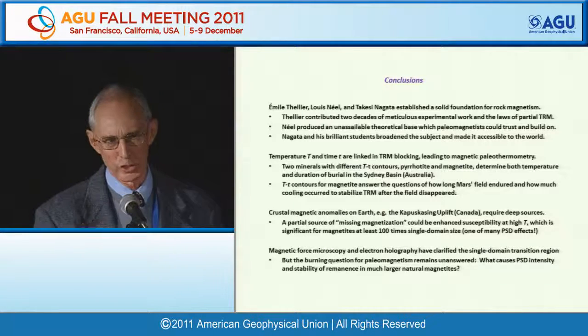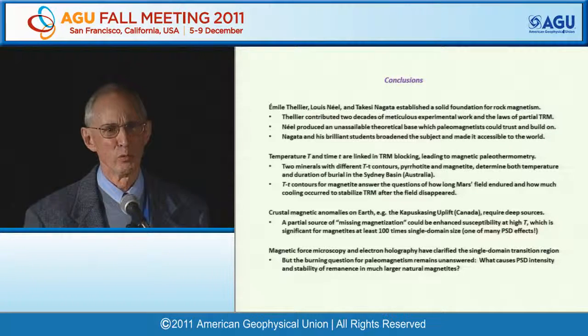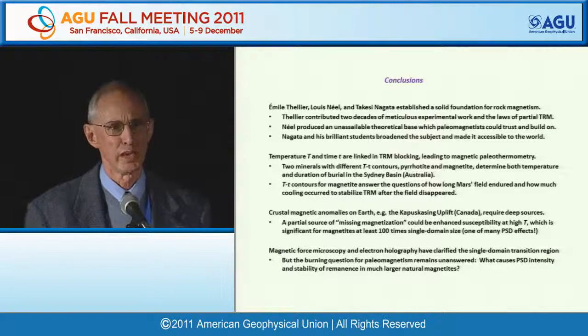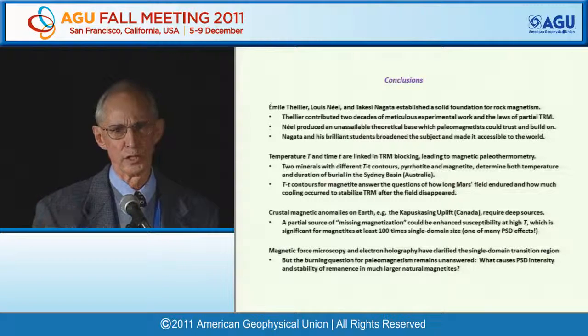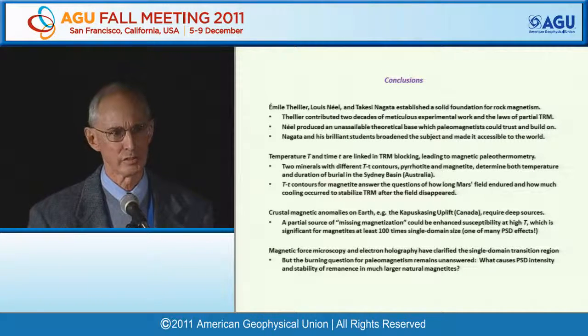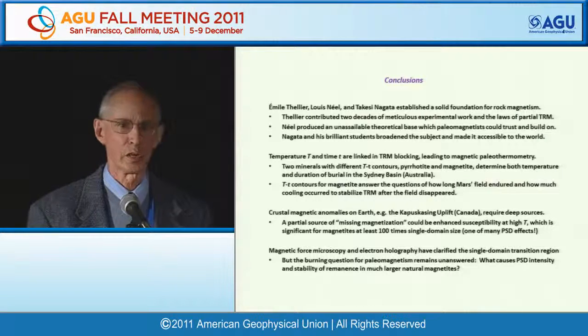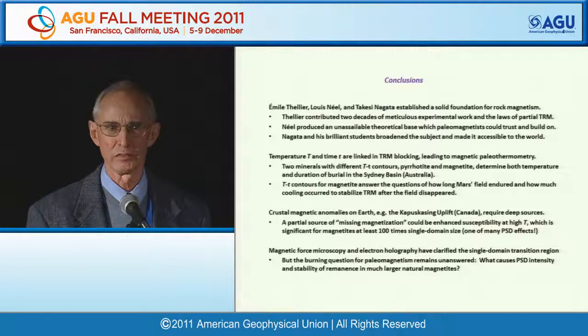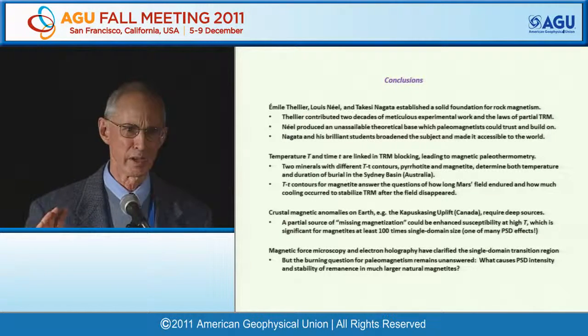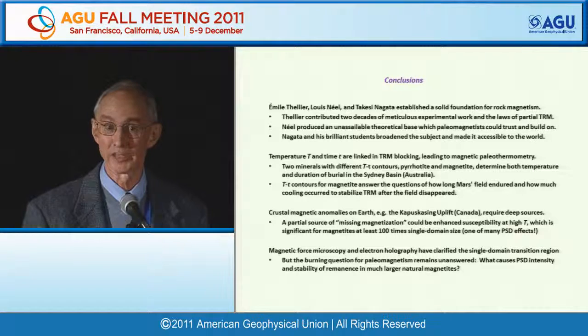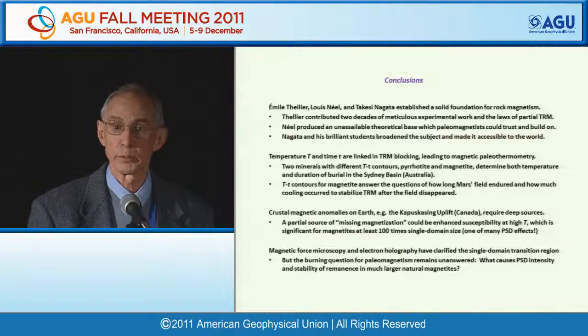The question is, when one uses low temperature demagnetization, which consists of cooling through the magnetite Verwey transition in zero field and then returning to room temperature also in zero field, you erase a fraction of the remanence. The larger the grain size of magnetite, the larger the fraction that's erased, leaving you with a residual that has really very single-domain-like properties.